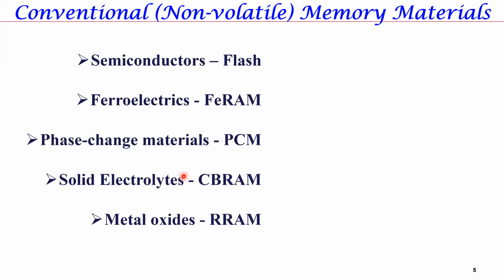And then you have ionic-based memory. Two kinds of those are solid electrolytes, where metal ions can suddenly diffuse into a solid electrolyte, or metal oxides, where you have vacancy ions that exist within an oxide. In all of these cases, the main modality is you're measuring or observing a change in the resistance of this device as this phenomena emerges.